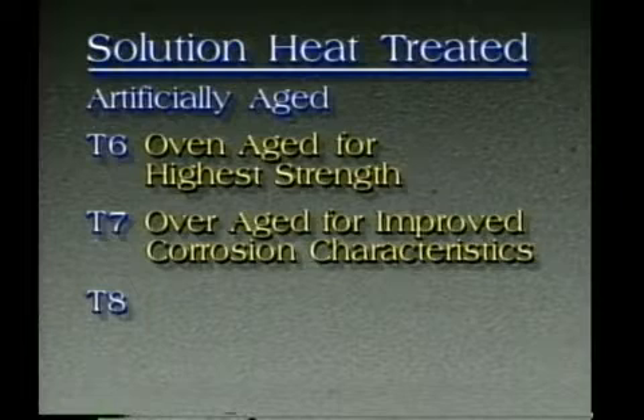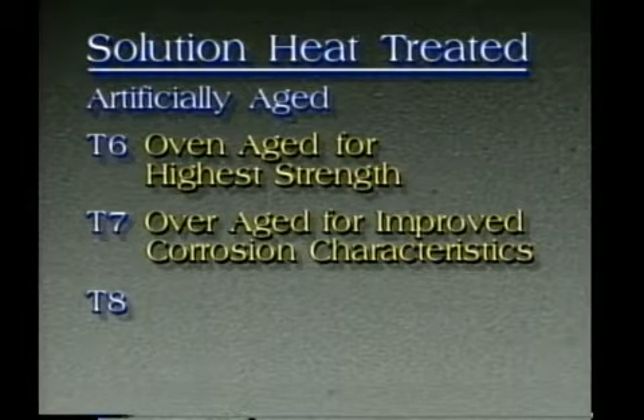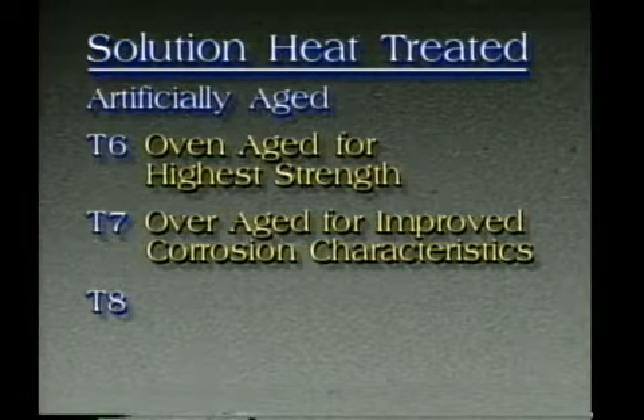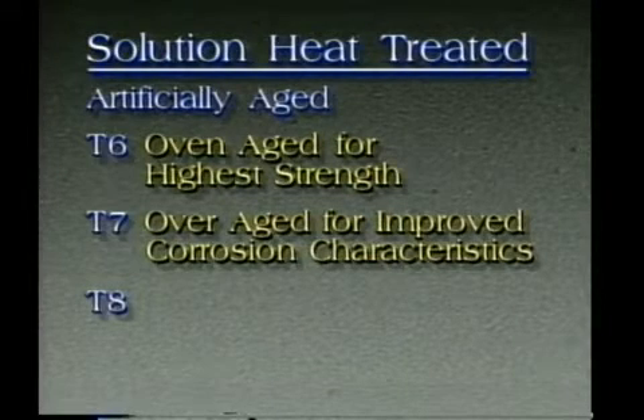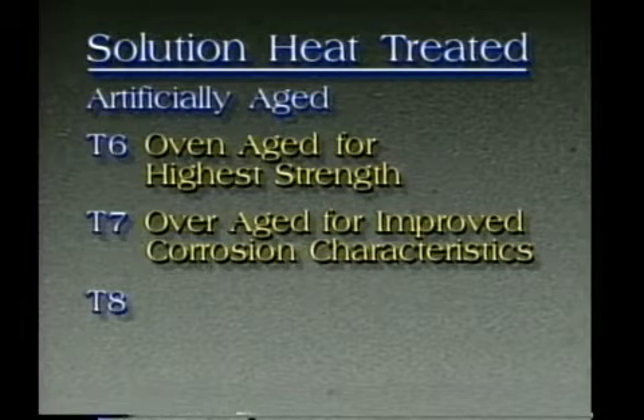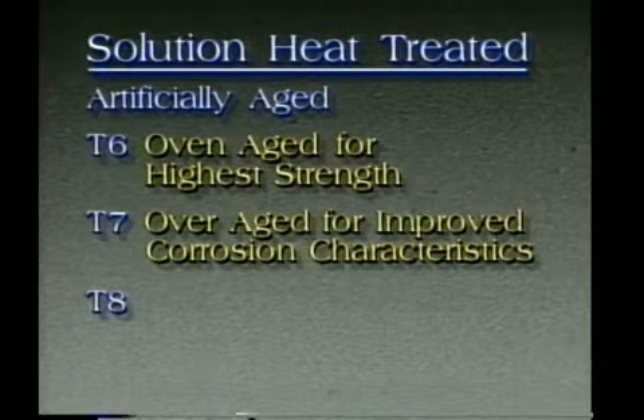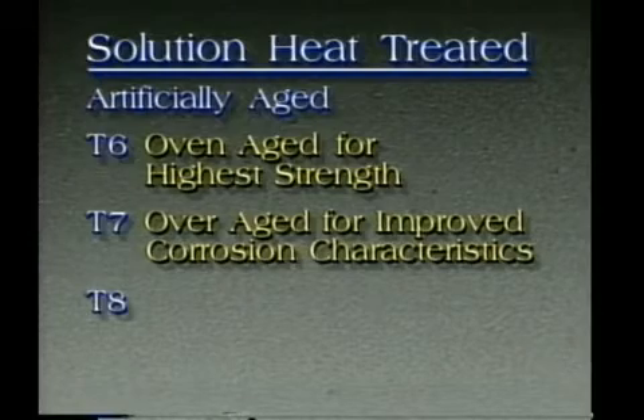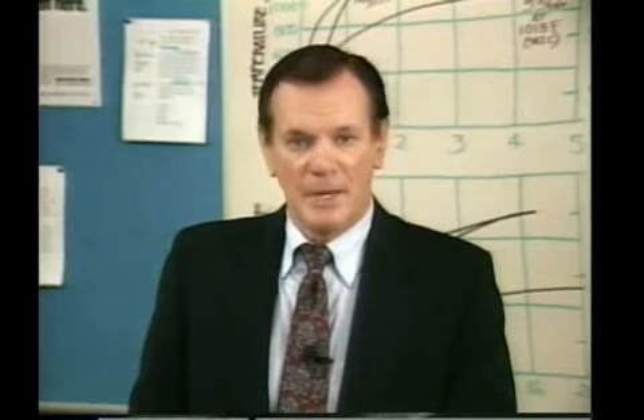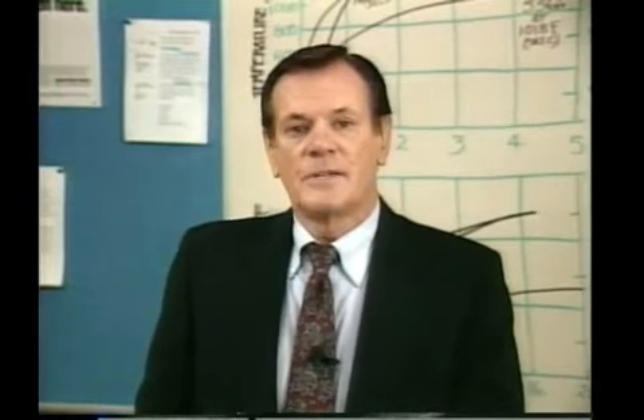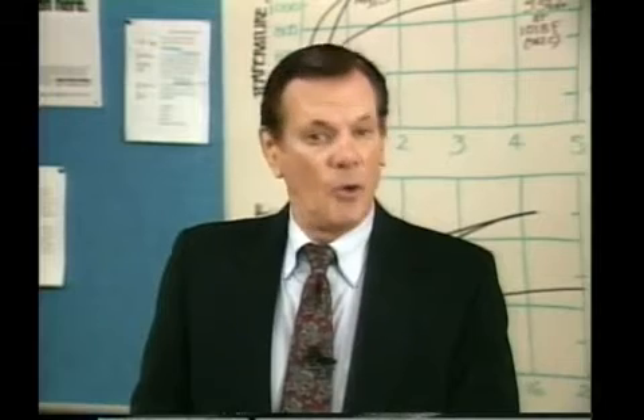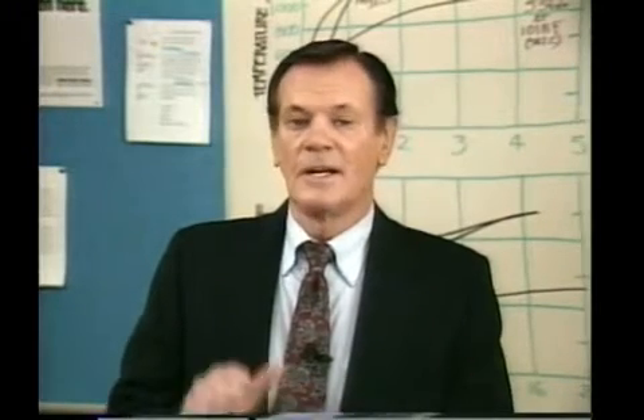The T7 temper involves artificially aging to achieve some special characteristics at the sacrifice of strength. In most cases, the objective of the T7 temper is to improve the stress corrosion or exfoliation corrosion characteristics of the 2000 and 7000 series alloys. T7 tempers are also used to achieve improved dimensional stability. These characteristics are accomplished by overaging. That is, aging is conducted at a higher temperature than that which is used for the maximum strength T6 temper.